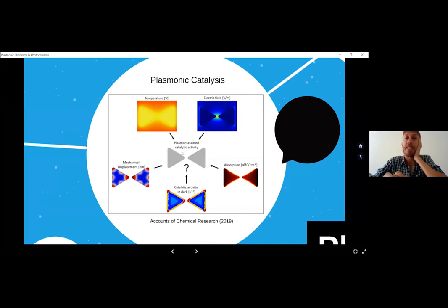And also these are metallic materials, and as any metal material or as any heterogeneous catalyst, it has an inherent response due to the uncoordinated atoms on the surface, right? So this would be like the catalytic properties of the material in the dark without any kind of illumination. So at the end, if we want to understand the reactivity of these plasmonic structures towards catalysis or some chemical reaction, we need to consider all these phenomena that happen at the same time. But also, if we think on an ideal reactor chamber for a catalytic reaction, many of these properties are really well desired as well. So indeed, the idea of thinking these plasmonic structures as reactors for chemical reactions is not far from what we do macroscopically nowadays for driving catalytic reactions, right?